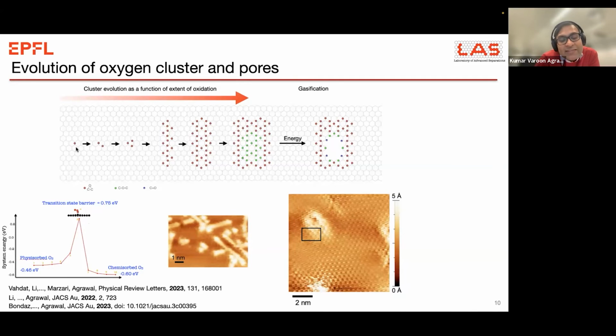All right. Then something very interesting happens. Usually you would think that when you are making an oxidized material, it will be very amorphous and have no order. But what we started realizing over time, and indeed we were very lucky, is that there is an order in these oxygen groups. They essentially organize themselves nicely in a predictable orientation, and they make dimers, trimers, and then they make a trimer chain. These chains are running linear. We could see them by scanning tunneling microscopy. What you are seeing is an oxygen chain running on graphene.